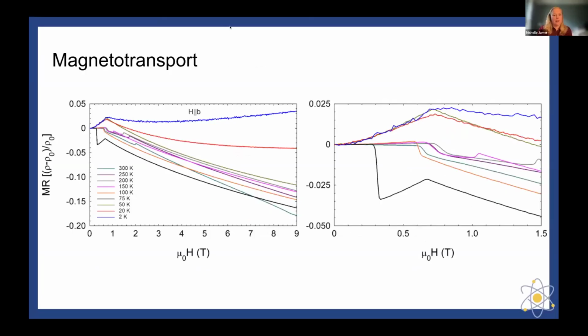So now if we were to take a look at all temperatures along the B axis, just so this way we can take a look at what it looks like holistically, the blue curve is 2 Kelvin, the black curve is 75 Kelvin, and the curves in between the two are basically all the other temperatures. So what we note here is that the magnetotransport along the B axis is super interesting because not only do you have that positive magnetoresistance up till 0.75 Tesla for almost every single temperature, what you also have is a little discontinuity along the magnetoresistance.